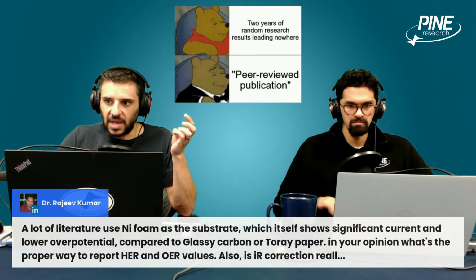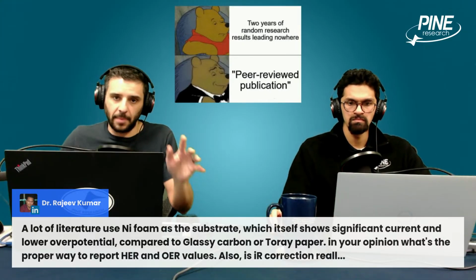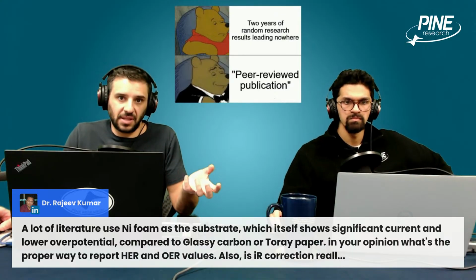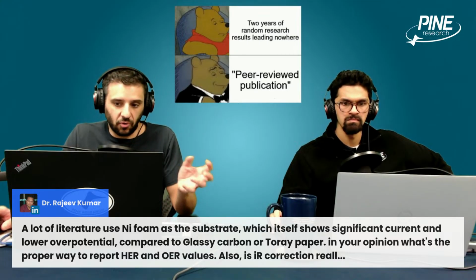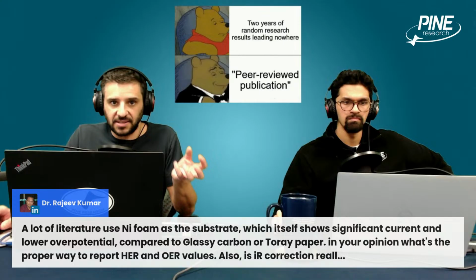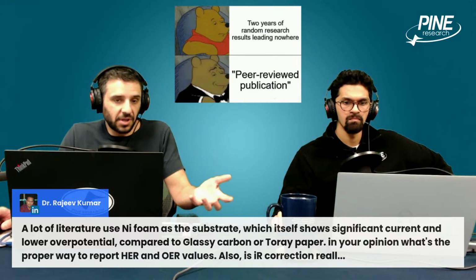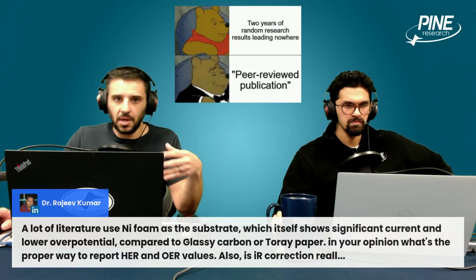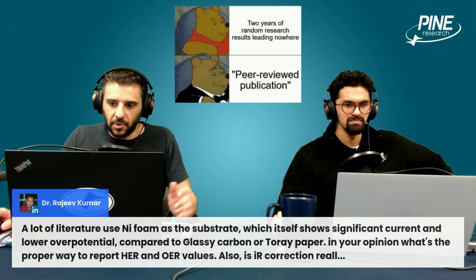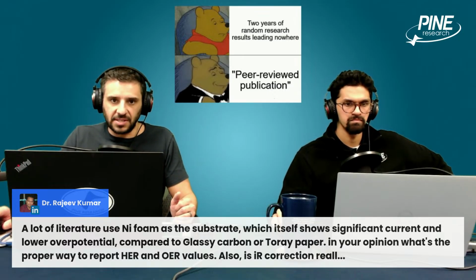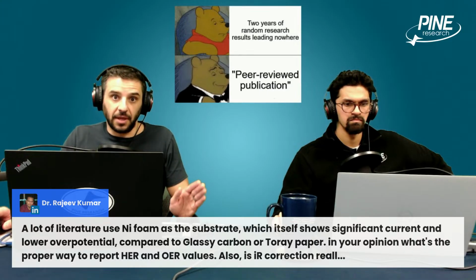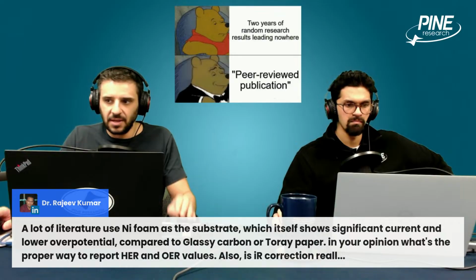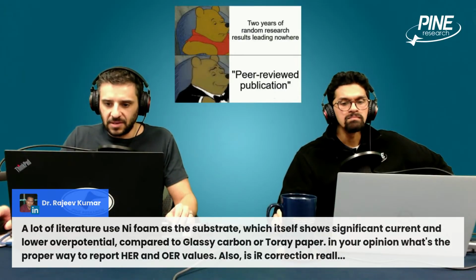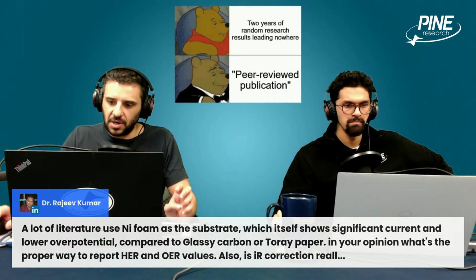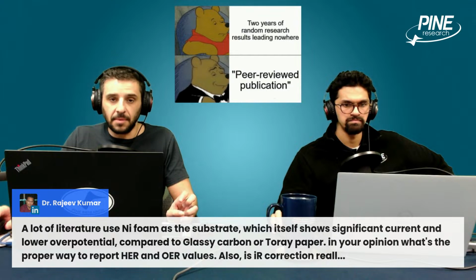But as a general idea, your comment is very wise, because you're pointing out something that's just true, which is that not everything can work great as a substrate, because if its intrinsic activity is a little bit too high or good or whatever, well, you don't want it to interfere if you're trying to study the activity of something else, which is why graphite, carbon, glassy carbon, Toray paper, all these things are really great and used a lot, because carbon is electrically conductive. It doesn't work great as a catalyst, and it does almost nothing. It's perfect in a lot of cases. It's the fuel cell, electrolyzer substrate, etc. So that's kind of my answer to that part of your question. To the last part of your question, is IR correction really necessary in reporting the values? In most cases, no.